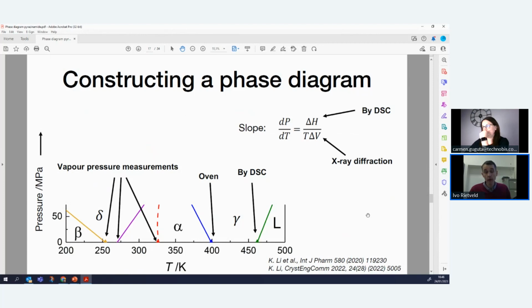And after that, you can even relatively easily, even without measuring anything under pressure, put a pressure element in too. You do that by the Clapeyron equation, which is shown up there, where you get the slope, dP/dT, of a certain equilibrium within a pressure-temperature phase diagram. That just depends on the enthalpy of transition, so the enthalpies that we obtained out of our DSC measurements, and obviously the equilibrium temperatures, but also the delta V, that is the change in the specific volume on a transition. And that we have been able to determine with X-ray equipment as a function of the temperature. Those were the curves that I showed on the left in one of the previous slides. So this is in principle possible in any laboratory that is relatively well equipped with X-ray equipment and DSC equipment.